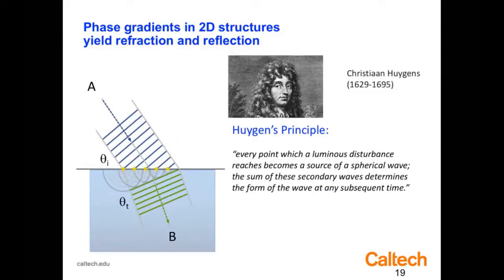And if I am able to adjust the relative phase of these scatterers, I can now, regardless of the refractive index of this medium or this medium, bend the light just due to the phase shifts and the gradient in the phase along this surface. So that's going to be the fantastic principle that allows us to take nanophotonic two-dimensional structures and manipulate light and make lenses that are as flat, sub-wavelength in thickness. So this is a very vivid illustration of this.